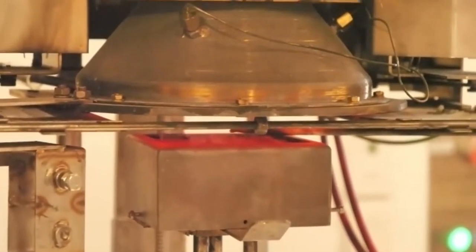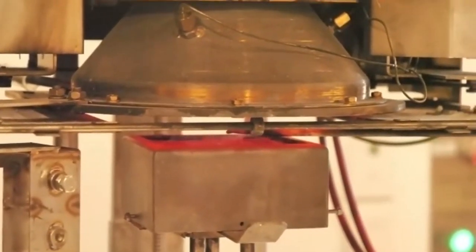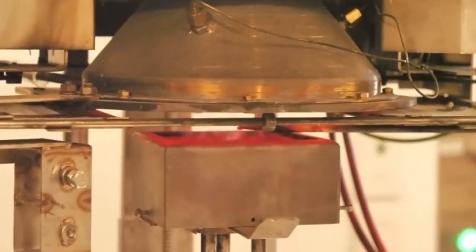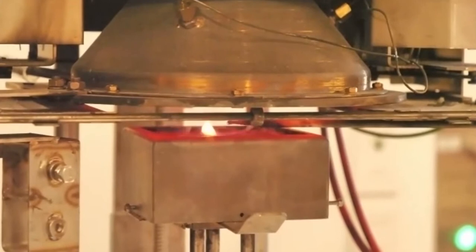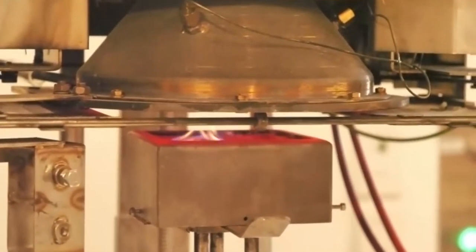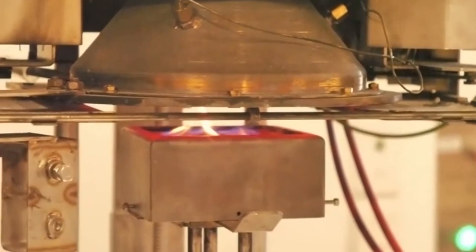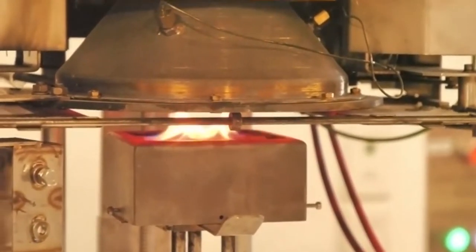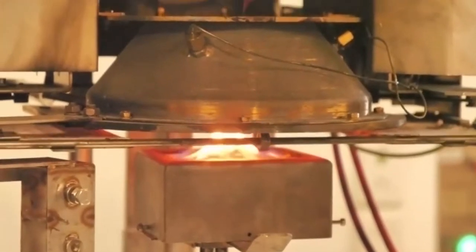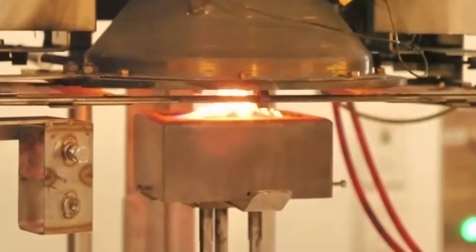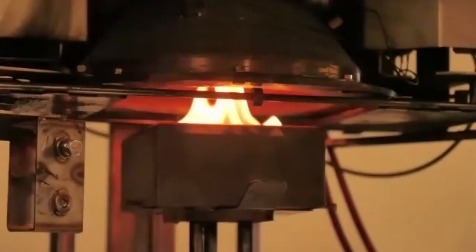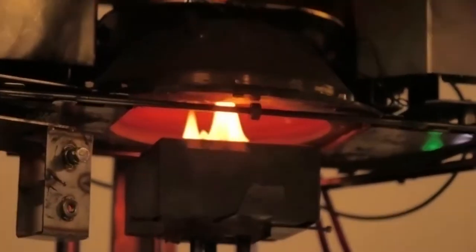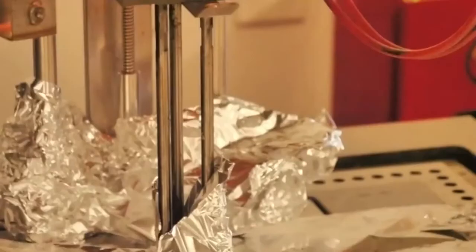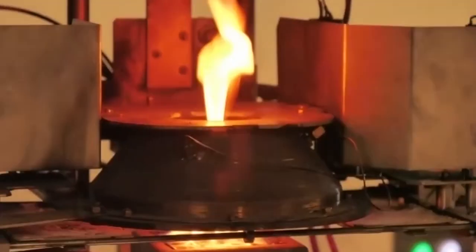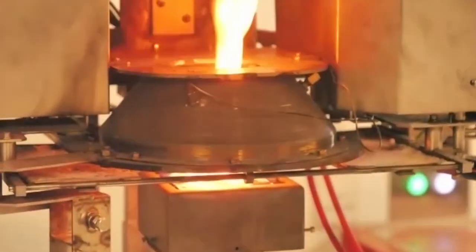Those gases that we can see here are pyrolysis gases, flammable gases that when mixed at the right conditions will create a flame. When that occurs, we will have an ignition. What is occurring at the moment is that the flammable gases generated because of the heat provided from the heater are in sufficient amounts that, when mixing with oxygen, they create a flammable mixture. Now, when that occurs, we see this visible flame. And this flame is essentially the amount of energy released. This is the combustion that is taking place in the gas phase.